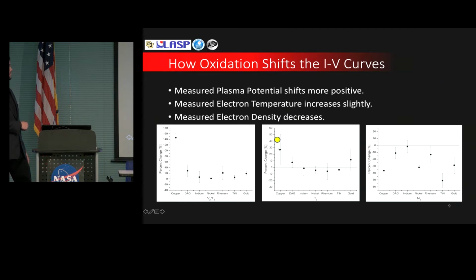However, for copper and the rest, you can see that there is a shift to the right, meaning that if you measured the temperature via an oxidized Langmuir probe, you would measure a hotter temperature than is expected. And pretty much across the board, the measured electron density of the plasma decreases. So as a general rule, if you were using an oxidized Langmuir probe, you'd expect a more positive plasma potential than what is real, a hotter electron temperature than what is real, and a lower electron density than what is real.